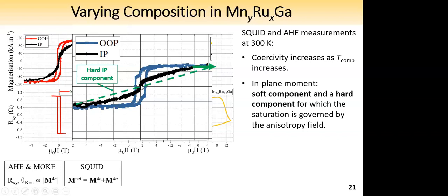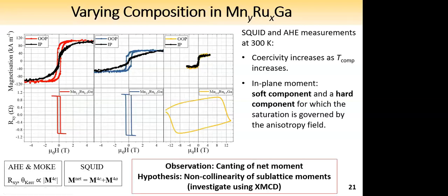However, what happens with the soft component? I propose that at 0 field, we have a cone of the magnetizations. Upon applying an in-plane field, this cone collapses into one preferred direction that's basically given by the field. That gives you this little jump, and then later we can see the rotation as we would expect. So our observation is canting of the net moment, and this corresponds to our hypothesis of non-collinearity of sublattice moments that could arise from competing exchanges, as I explained in the previous slide. I will discuss this in more detail and investigate using XMCD.